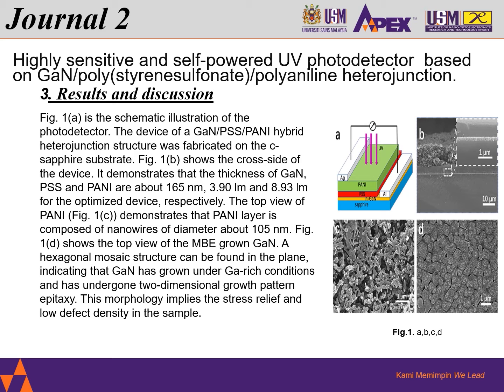The top view of PANI, figure 1c, demonstrates the PANI layer is composed of nanowires of diameter about 105 nanometer. And finally figure 1d shows the top view of the MBE grown GaN. A hexagonal mosaic structure can be found in the plane, indicating the GaN has grown under Ga-rich conditions and has undergone two-dimensional growth pattern epitaxy. This morphology implies the stress relief and low defect density in the sample.